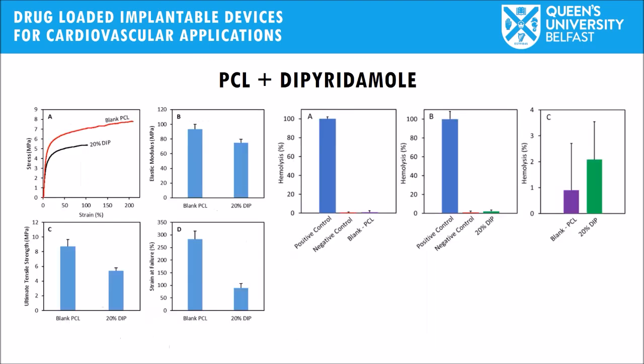We tested, in this case, dipyridamole, which presented more interesting properties and better mechanical properties than the vascular graft prepared using aspirin. So we tested the mechanical properties of the resulting grafts and the hemocompatibility of the materials, showing that they were highly hemocompatible. And obviously, because of the nature of PCL, polycaprolactone, the polymer used to prepare those grafts, we can see that the incorporation of dipyridamole reduced the ultimate tensile strength and the strain at failure.